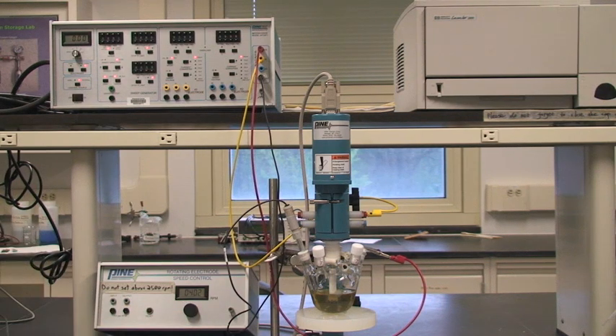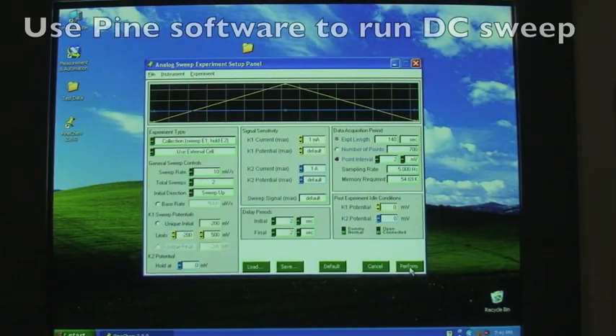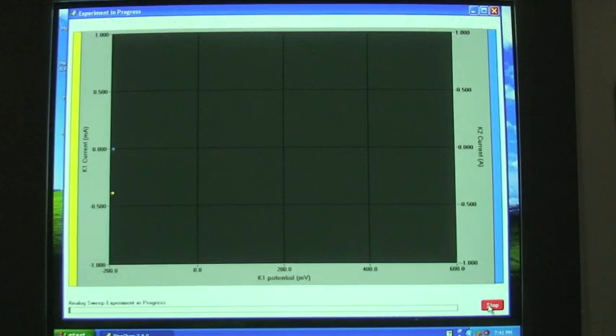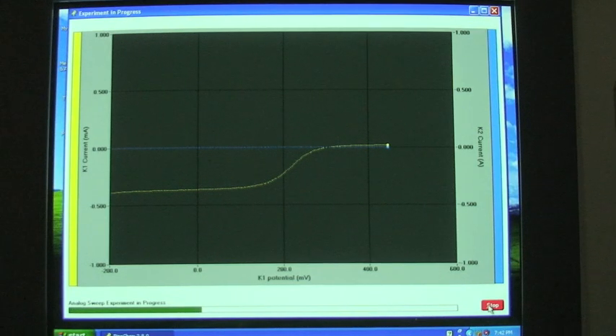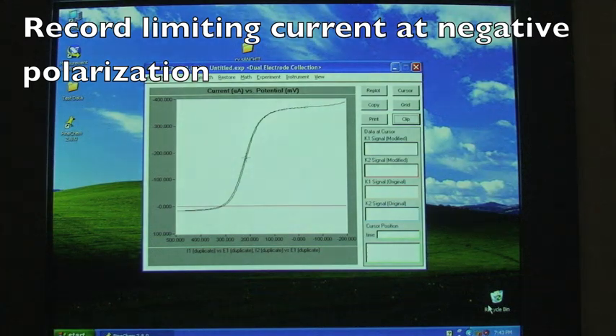At no point should the electrode be allowed to spin above 2500 RPM, as this could result in damage to the electrode. Once the rotation speed has been set, we will use the PineChem software to perform a linear sweep. This time we are interested in just the oxidation of ferrocyanide and will only be performing an upward sweep. The sweep should show a somewhat flat current behavior at more negative potentials for the working electrode. This value is the limiting current, and it is the maximum current allowed by the mass transport limitations present in the system. This behavior could be observed in the first two sweeps, but at a lower magnitude when the solution was unstirred. Record the value of the limiting current once the sweep has completed.